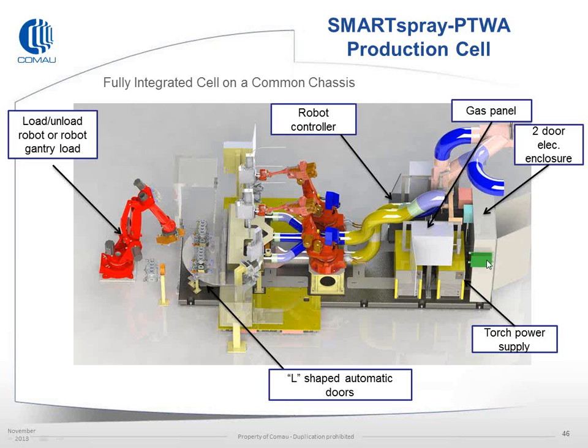The basic layout has your power source and control panels in the back, and you'll notice there's two dust collection tubes. The lower tube is actually a returned recycled air for the cell. It is flown into the bottom of the case and flown up around the block. This helps to cool the block as well as direct any of the overspray, and it helps to minimize any overspray in the crankcase side of the block. The upper tube, here shown in the original concept with three tubes coming to the top, are the suction phases, and these provide approximately 5,000 CFM of suction to pull out any exhaust as well as overspray at the top of the blocks.